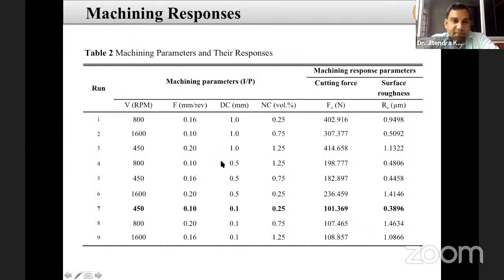So this is the response parameter, whatever Taguchi we have obtained, and according to that we calculate the forces, and also we calculate the surface roughness with the portable surface roughness tester. We obtain that the 0.25 nanoparticle concentration, with 0.1 feed rate and 0.1 depth of cut, gives the better surface roughness and the lower cutting forces, which is our objective of this work.